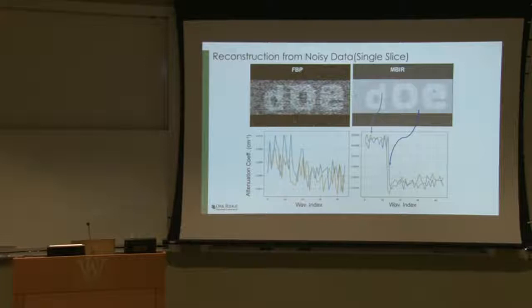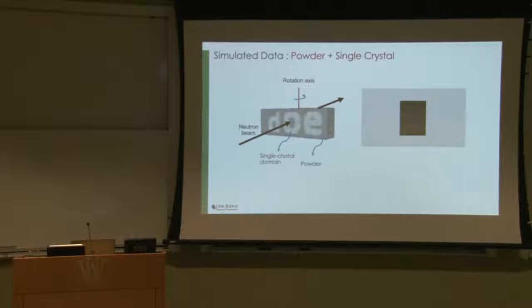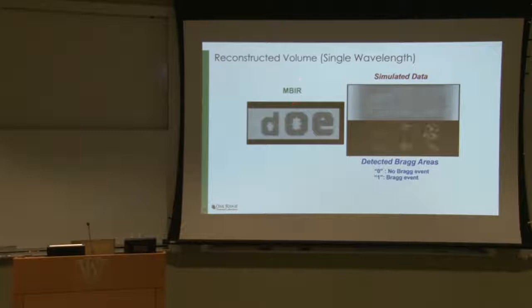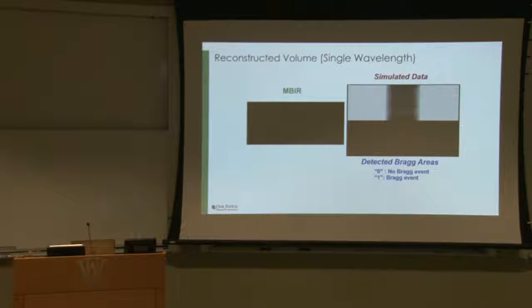When you have single crystal data with the flashes occurring due to Bragg scatter, like over here, along with the noise, that's an additional layer of complexity. And then the proposed algorithm can still obtain a 3D reconstruction compared to the existing technique. So what you're seeing is the reconstruction. And you can also see a map. So it goes to the original measurements and also tells you which measurements were left out finally at the end of all the iterations. So you get two pieces of information out of this, and it shows you can do tomography even for single crystal materials.